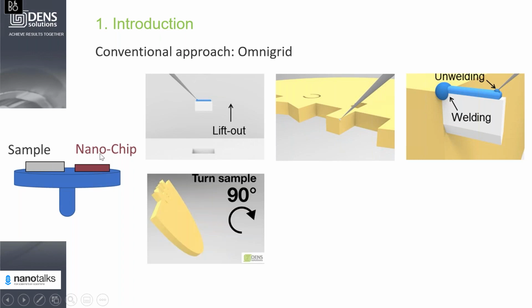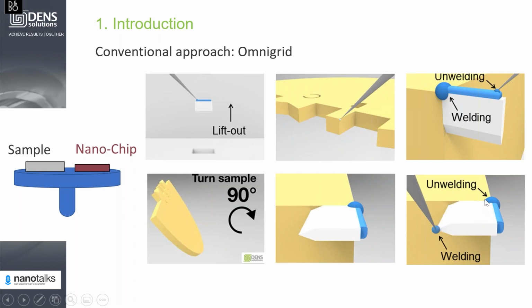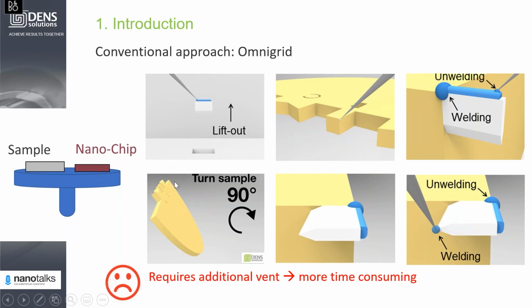So the way out, which happens in the majority of cases, is that you need to open the chamber of your FIB. You need to manually rotate the OmniGrid 90 degrees to have the right orientation. From here, you insert the manipulator, weld it to the lamella, unweld it from the OmniGrid, and then you can transfer it to the nanochip. There are a few issues with the current approach. First of all, it requires an additional vent of your FIB, which makes the whole process more time-consuming. And secondly, just because the welding and unwelding happens after the sample has been prepared, the sample might be contaminated with platinum.